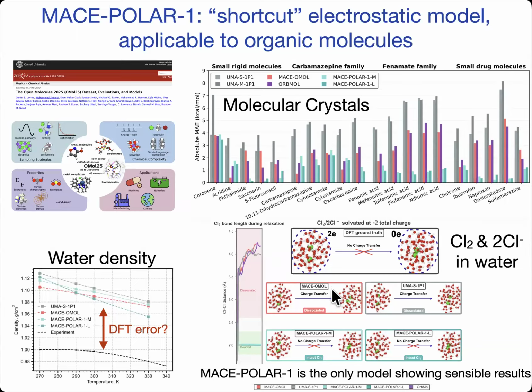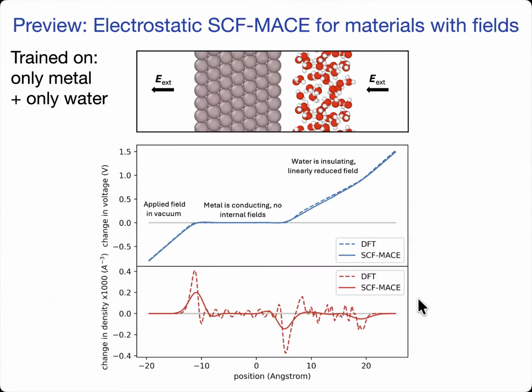If you run it with the non-electrostatic model, no matter how accurate, then there is charge transfer, a small amount of charge transfer between these two clusters that shouldn't happen, and all four chlorine atoms separate. And when you do this with a polarizable model, then this doesn't happen. So you don't get the charge transfer between the clusters. You correctly recover the fact that one of the Cl pairs separates, the other one doesn't.